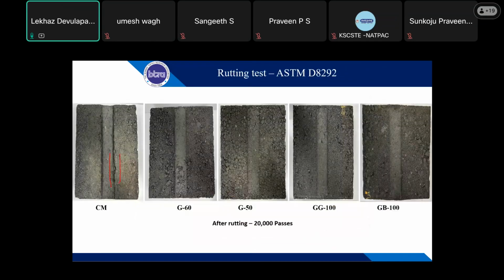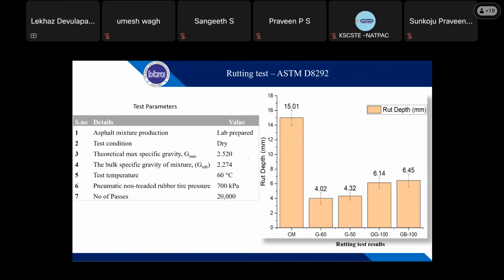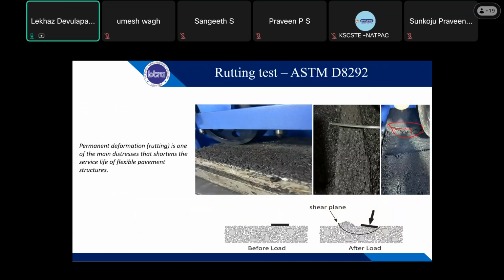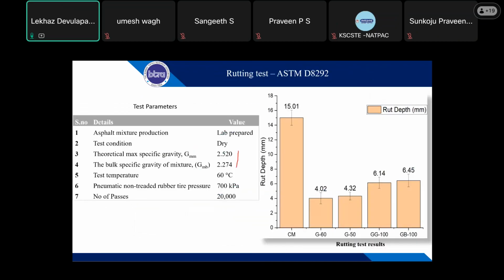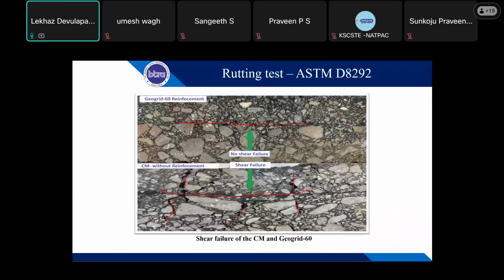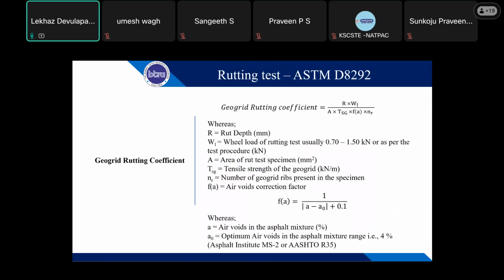If you see this one, the specimen should have 7 plus or minus 1 air voids. So suppose you calculate air voids of 6.2 percent or 7.8 percent, that will affect our coefficient. So we come up with a factor of air voids also, and then the number of ribs.